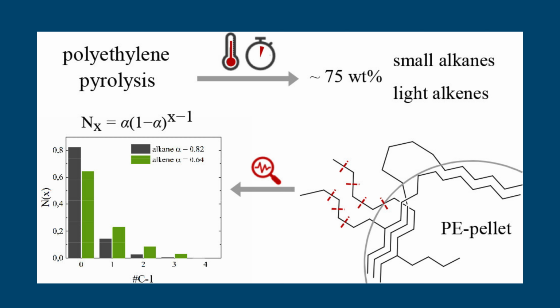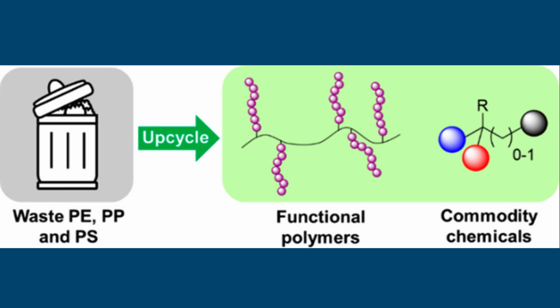For example, PE pyrolysis yields alkenes that rapidly aromatize. Even if side reactions were suppressed, the process remains highly energy-intensive due to the large heat of polymerization, e.g., 108 kJ per mole for PE. PVC preferentially undergoes dehydrochlorination, 250 to 320 degrees Celsius, rather than depolymerization. Consequently, direct thermal recycling of polyolefins is generally inefficient and non-selective.